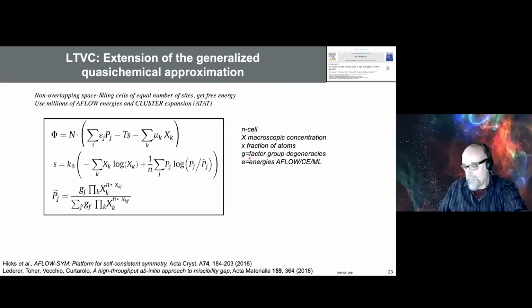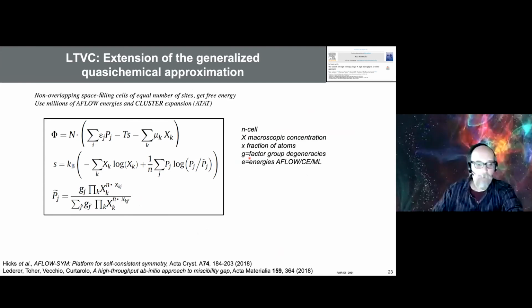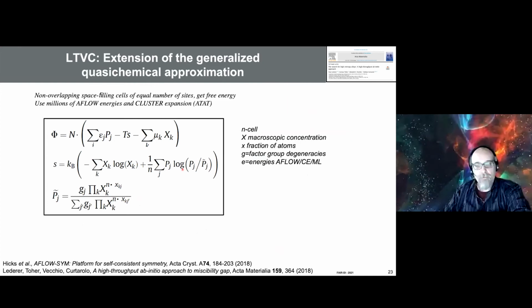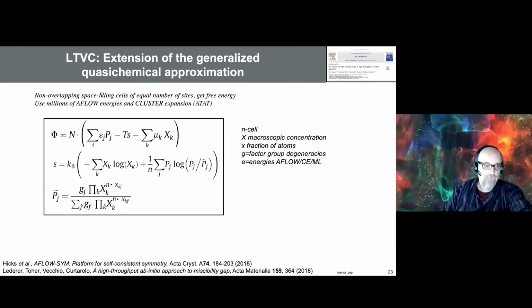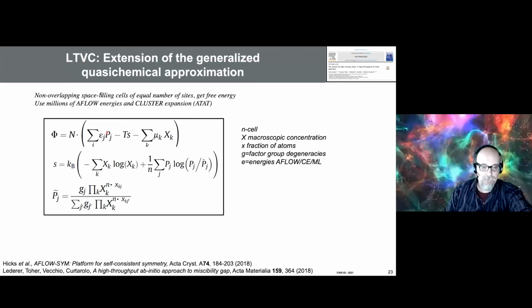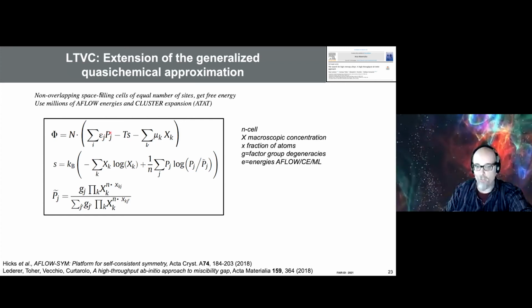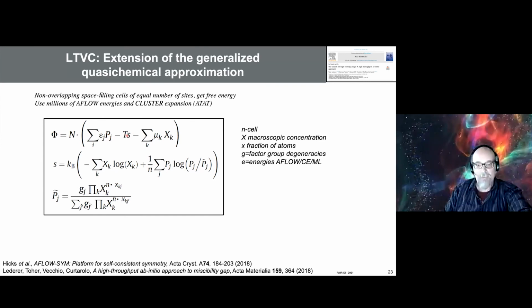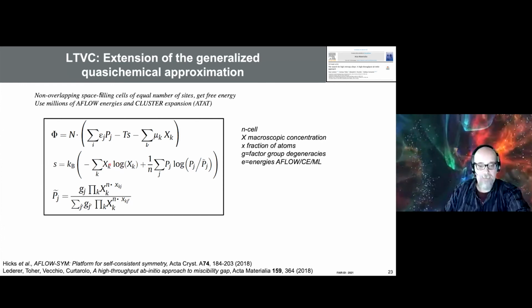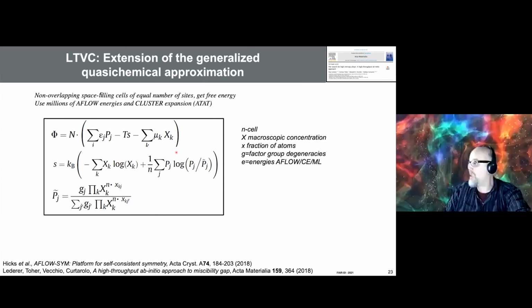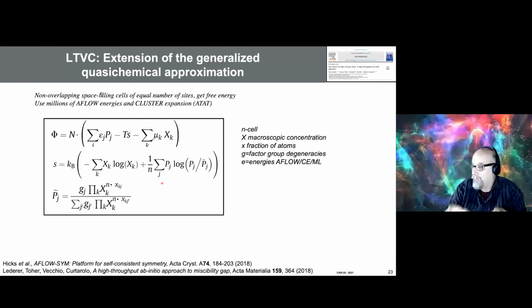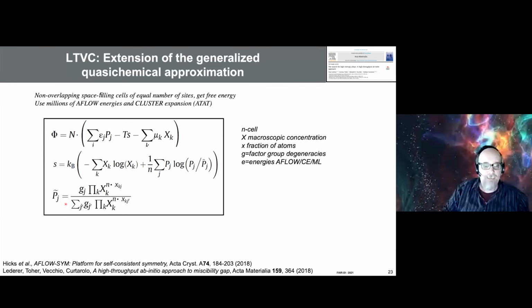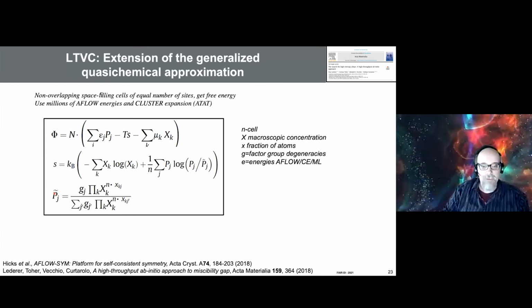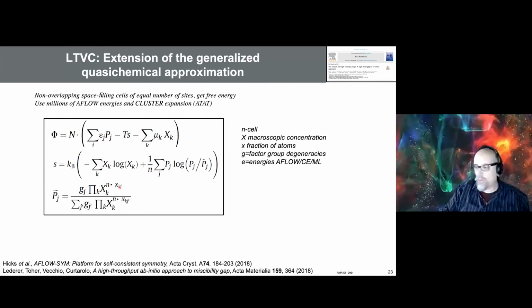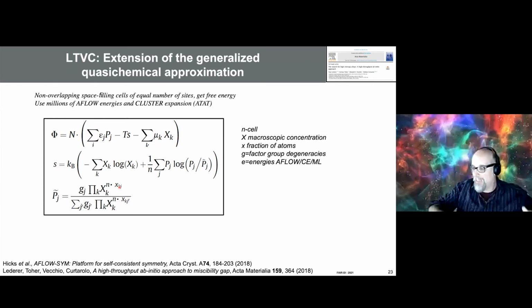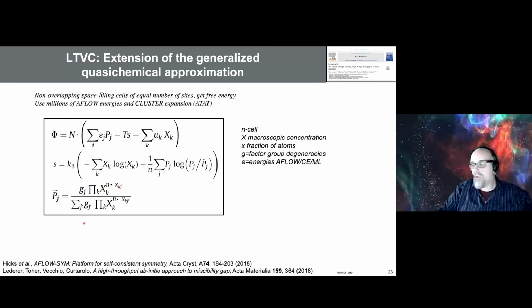Okay, so now let's go back to the big data. What do we do with this P? And why did we choose P? First of all, we want to get the disorder transitions, and you have these grand potentials with our probabilities. You don't know what they are, and we will find what they are later. You guess some entropy, which has the macroscopic concentration plus a change, and a change that you don't really know what it is, but we will discover it. Then you make these calculations, because you need to get the generation. Every tile has the microscopic compositions, and the microscopic composition sum needs to be the macroscopic. So this is pretty much the generation of every tile.